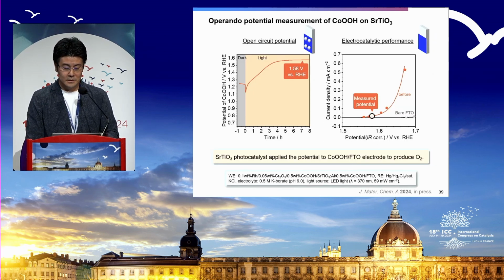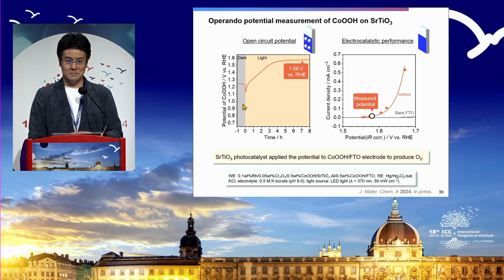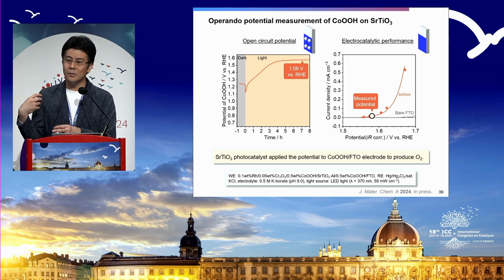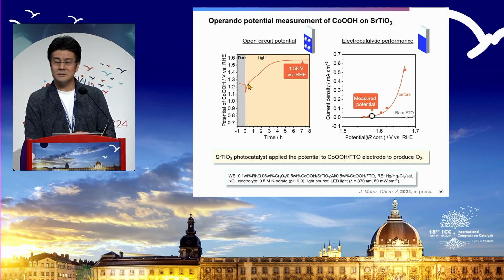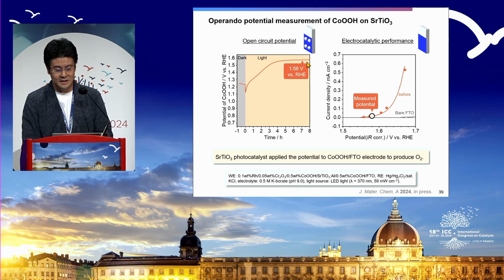And this is a result. We needed to wait a very long time because only part of the holes are coming to the cobalt electrode. So we started with the open circuit potential. You keep measuring this cobalt electrode. You start with around this one, it's the cobalt redox potential. And shining the light, you shift the potential getting closer to 1.58, which is the oxygen evolution potential, right? At the steady state, this particle, the cobalt oxide electrode, sees this 1.58 volts, which is the same as the oxygen evolution potential. You can now remove the powders and then measure the performance just by the cobalt electrode. And this is the electrode, right?